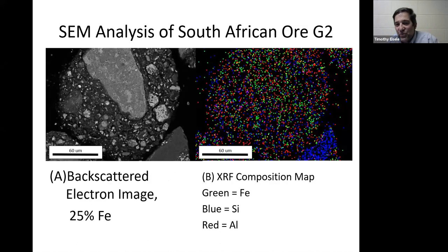So this ore here is one that I tested out. This came from South Africa originally. And this particular ore was extremely finely grained. And if you look at this X-ray map here from the electron microscope, the scale bar is 60 microns, the green is iron, and the blue and the red are silica and alumina. And you can see that there's no segregation between them. They're all blended together at a very fine scale, very submicron. And so it's not really practical to physically separate those. So we were looking at whether the bacteria could chemically separate them.